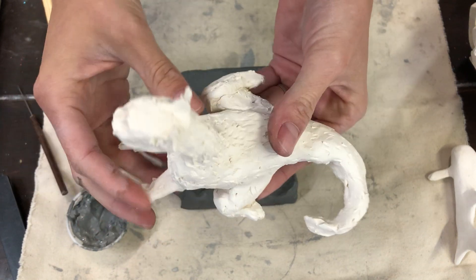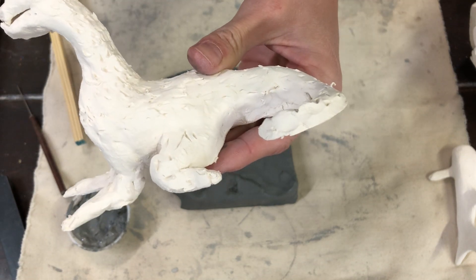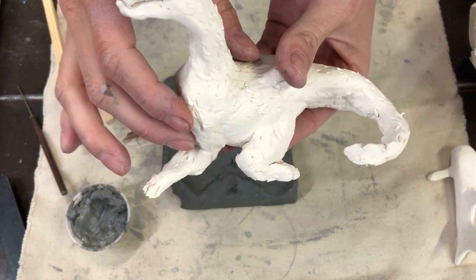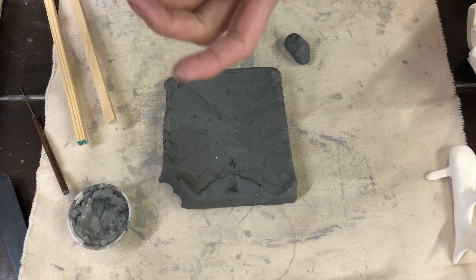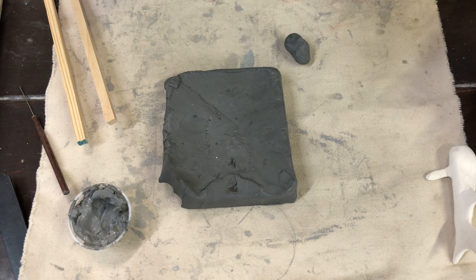Here's a really cool dragon, which brings me to another point. See how the body is pretty thick? You never want anything thicker than a golf ball. That means inside our dragon we actually hollowed out the bottom so it wouldn't have any accidents in the kiln. If you have anything thicker than a golf ball, flip the piece over and hollow out the inside using a spoon or any materials you have at home, so the walls don't get too thick and water can evaporate properly during firing.